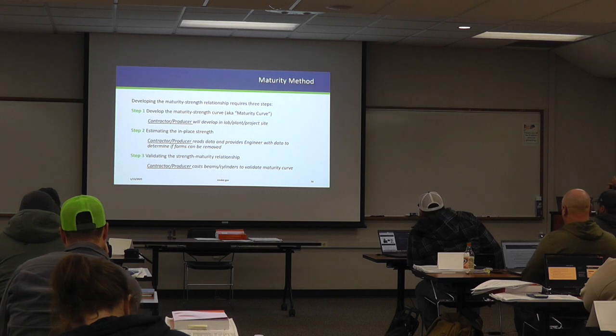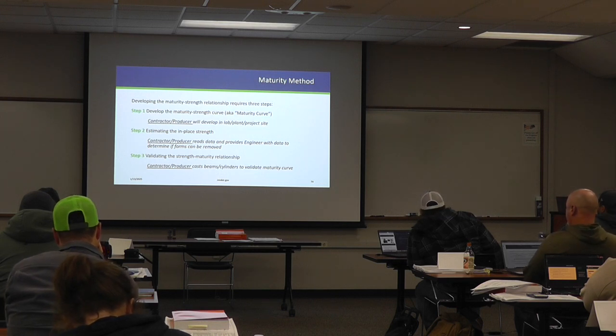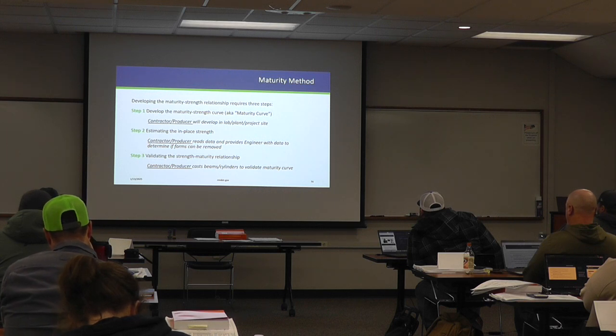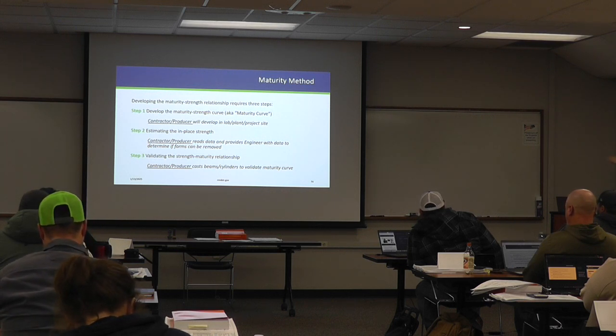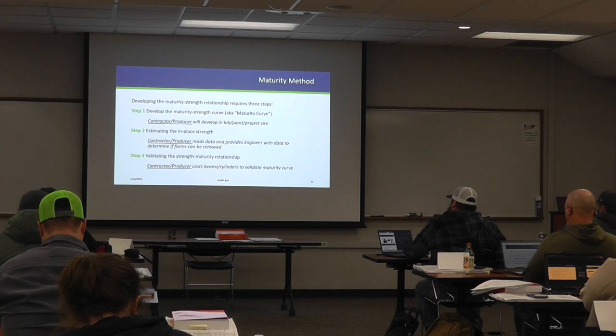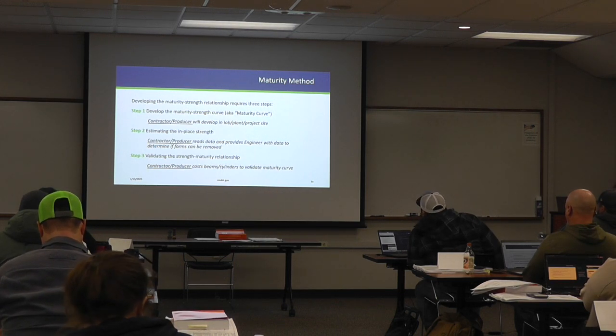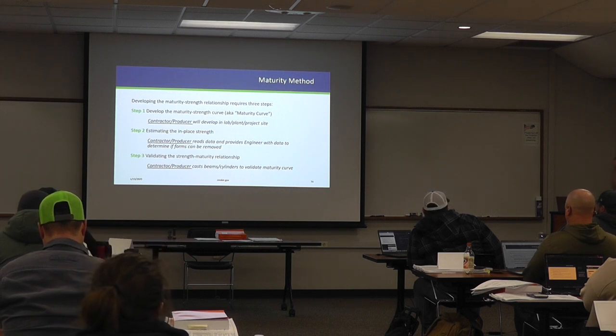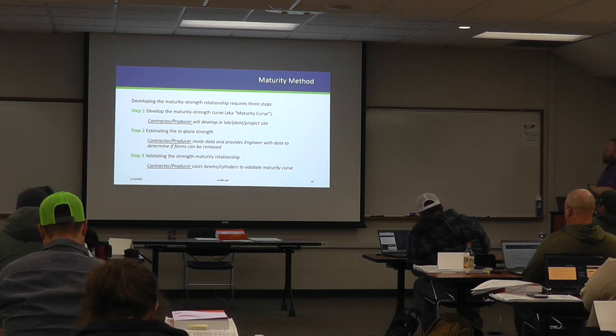If you are using maturity, then we've got to develop that maturity curve. So this is in the lab. They cast enough cylinders to get strength over time, and they're also logging temperature at that. That develops your maturity curve. Then when we're estimating in-place strength, we take that maturity curve, we plot the data from our sensors in the field that are taking temperature over time, and that gives us our estimated in-place strength, which is very accurate. And then we also have to validate that maturity curve relationship.